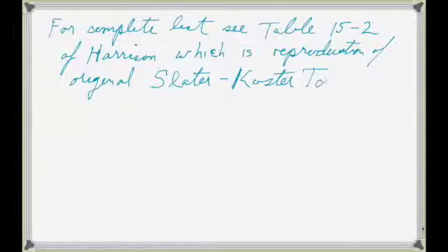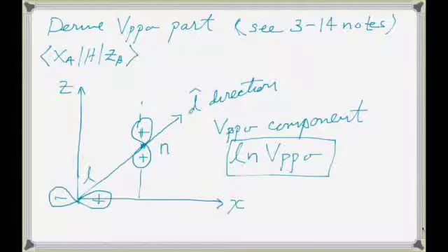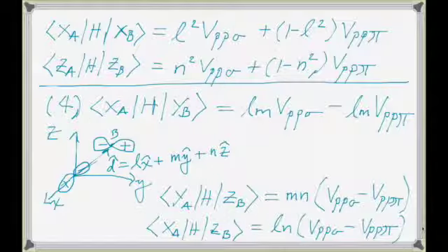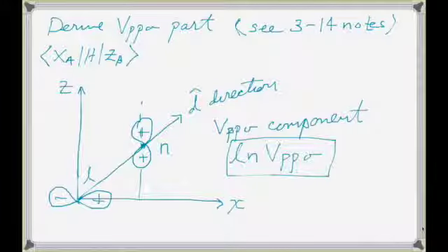They were the first ones to catalog all these values, like VPP sigma, VPP pi, and ditto for the d orbitals, and they also give the form of the matrix element, like what we've been writing down here. So this kind of expression for the matrix elements in terms of the direction cosines. And they also do that for the d orbitals, which are more complicated because they transform like tensors, so it's not quite so easy to derive those.